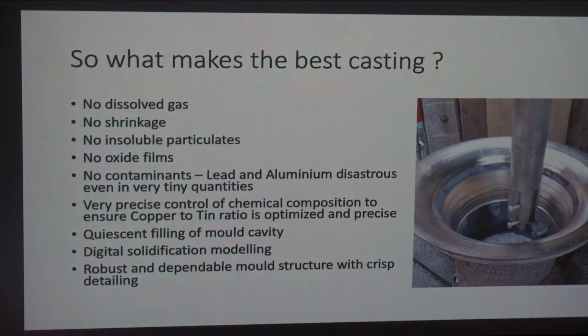So, what makes the best casting? Well, no dissolved gas, no shrinkage voids in the metal after it's solidified, no insoluble particulates, no oxide films floating around, no contaminants in the way of other metals, and lead and aluminium particularly disastrous, even in tiny quantities, and a very precise control of the chemical composition is crucial, because the composition ratio is vital to what sound the bell will make, and will vary according to the proportions of the bell. We've got to make sure the bell is a casting that's physically and mechanically strong enough as well as everything else.